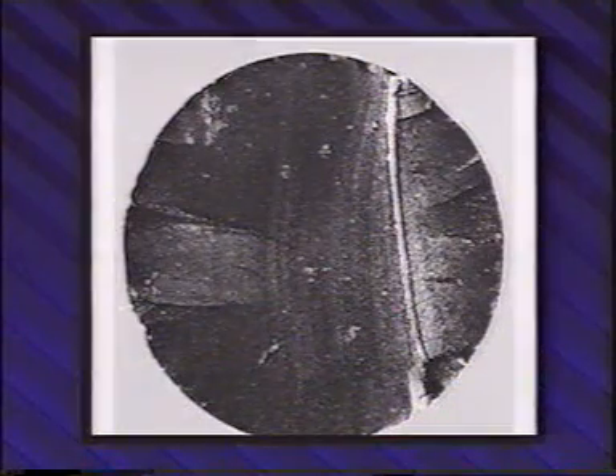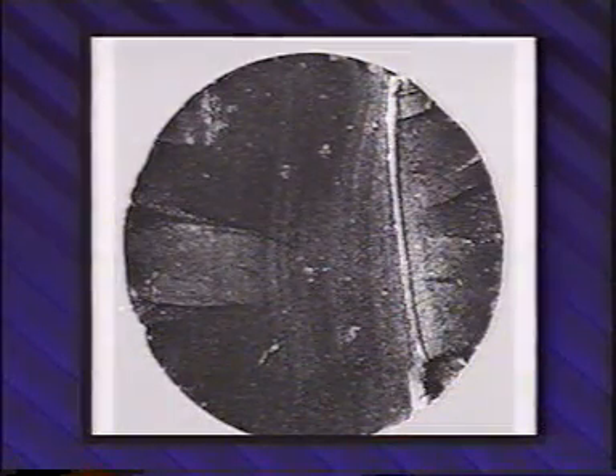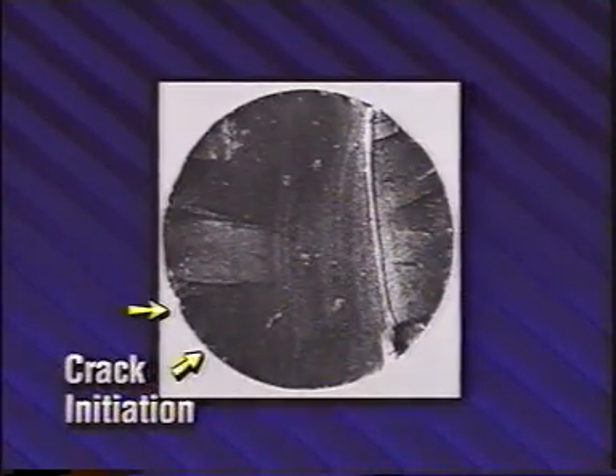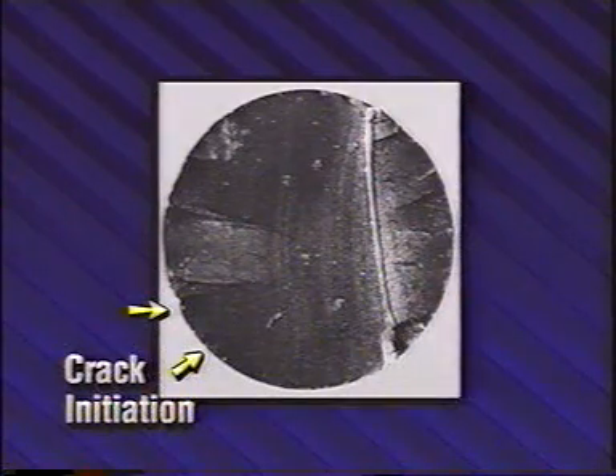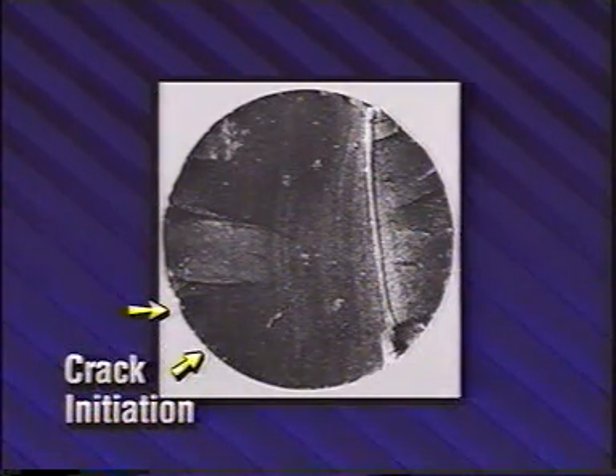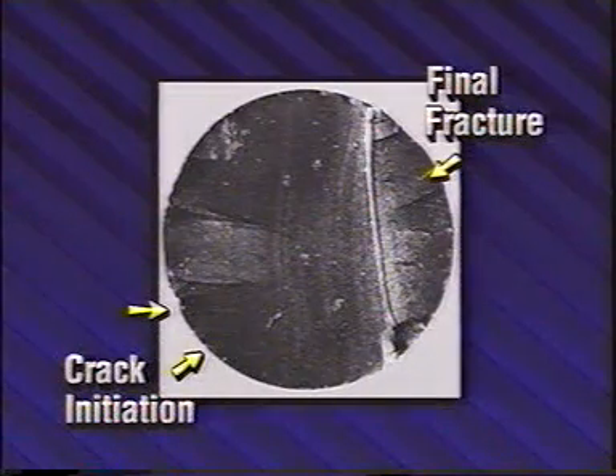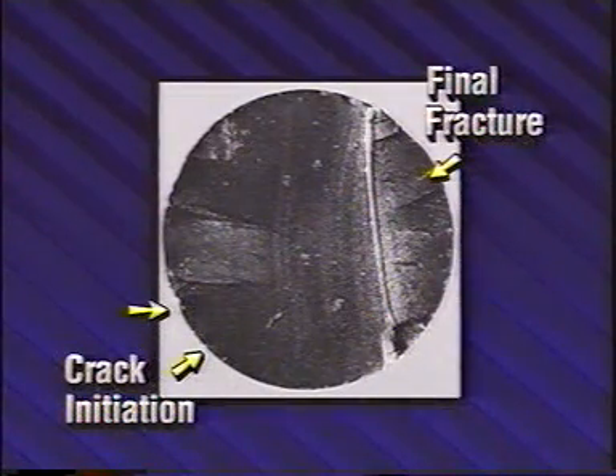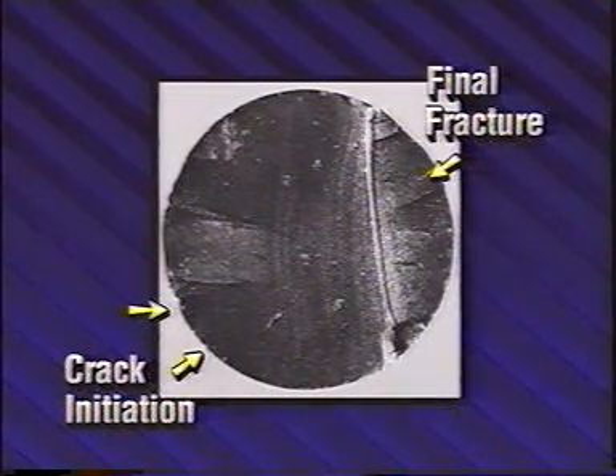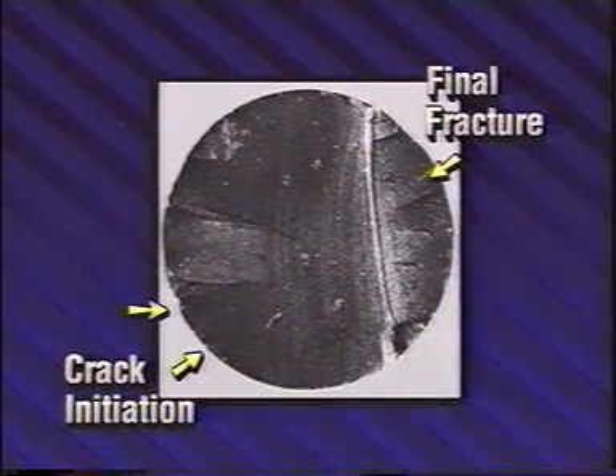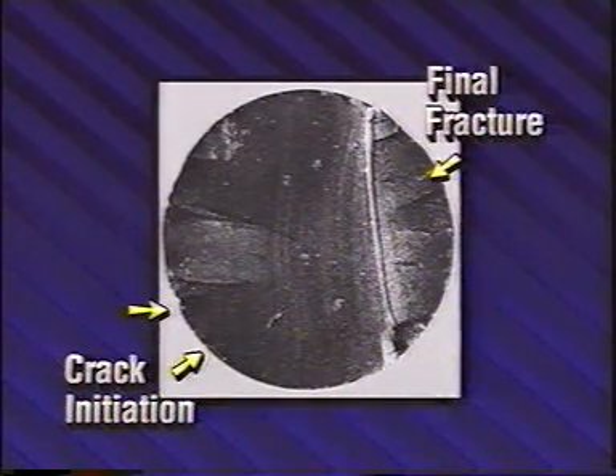The fracture surface of a typical valve stem failing by fatigue shows multiple crack initiation points. The crack propagated by fatigue through 3/4 of the stem before the final fast fracture occurred in a single cycle. The source of stress concentration was a geometric notch resulting from a crack caused by oxidation.